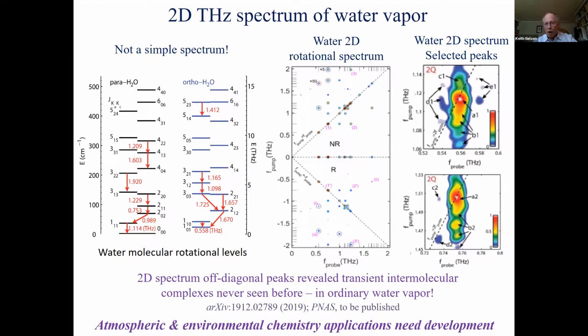Here is the same sort of thing in water, ordinary water vapor. It has kind of a complicated 2D spectrum, much like 2D NMR spectra, with lots of peaks that can look very complicated. I want to focus on just a couple of peaks and mention that they are only there because my dipole from one rotating water molecule interacts with the dipole from another one. These peaks revealed intermolecular complexes between water molecules whose existence was not known before. The amazing thing about that is water is about the most extensively studied molecule in the universe, so we might not have thought that there were many secrets left to reveal. But in fact, in the water vapor that's right around you right now, in whatever room you're in, from ordinary humidity, there are complexes being formed and unformed constantly in which molecules interact, and that's revealed by these unique off-diagonal peaks in our water 2D rotational spectrum.